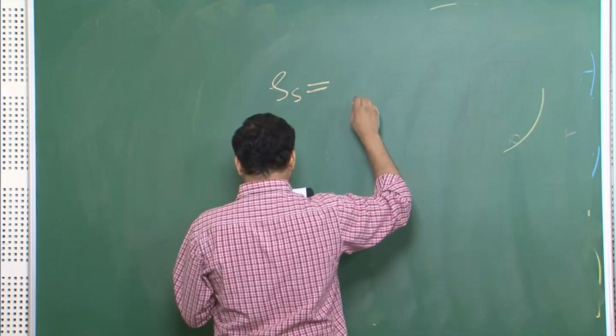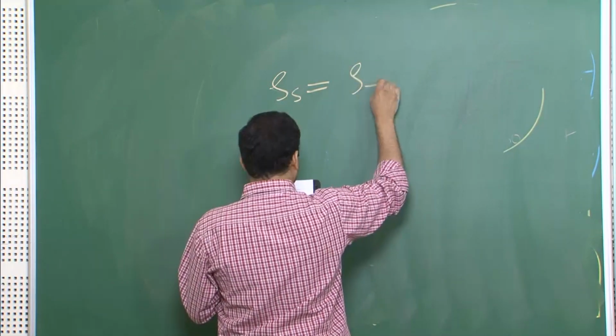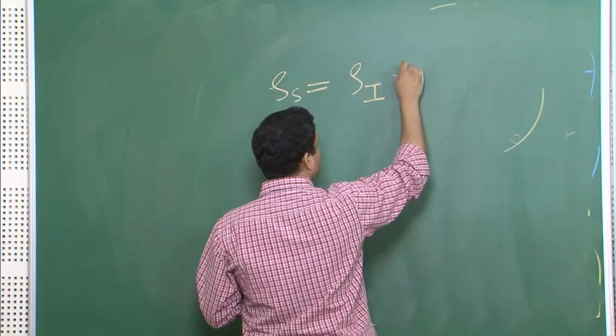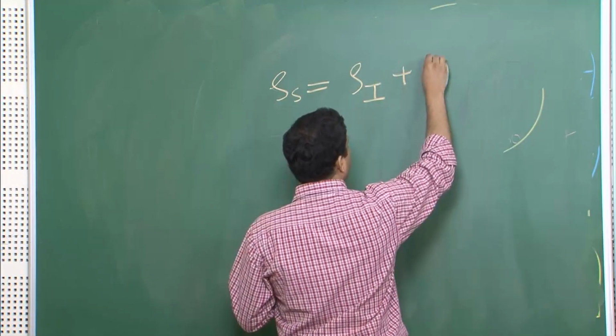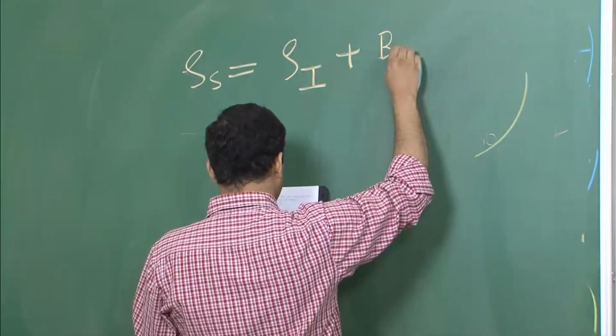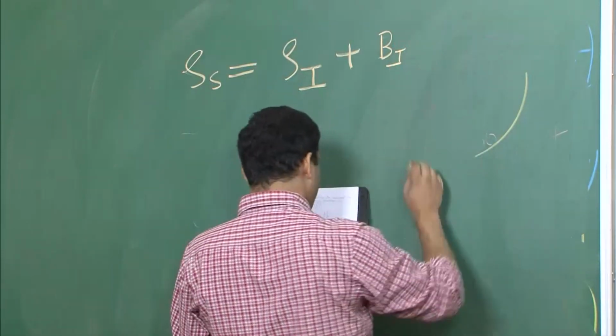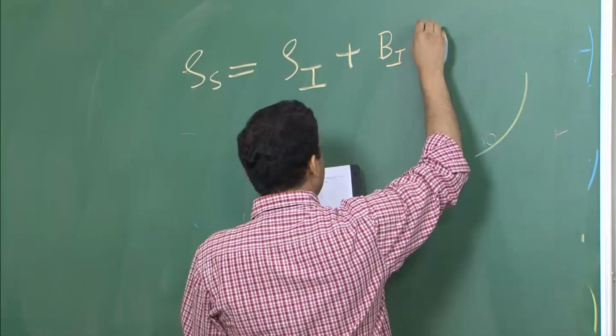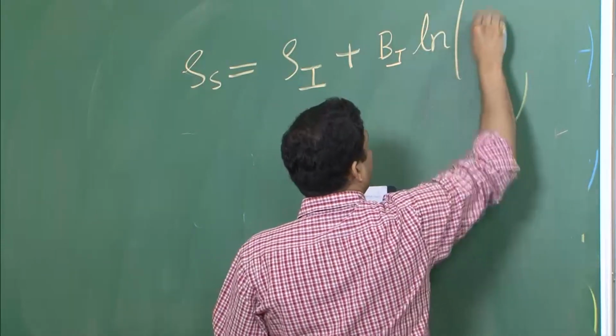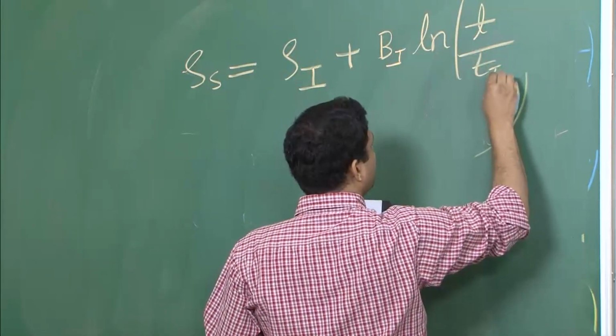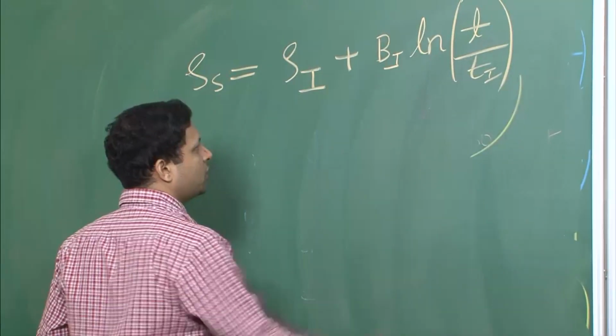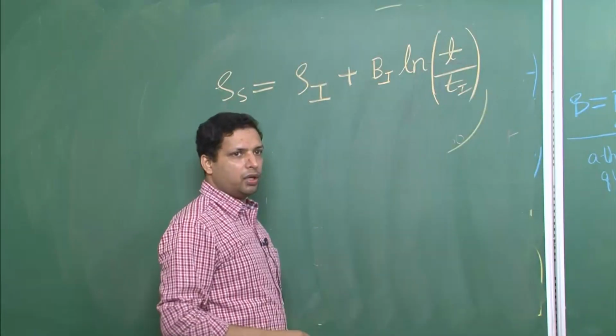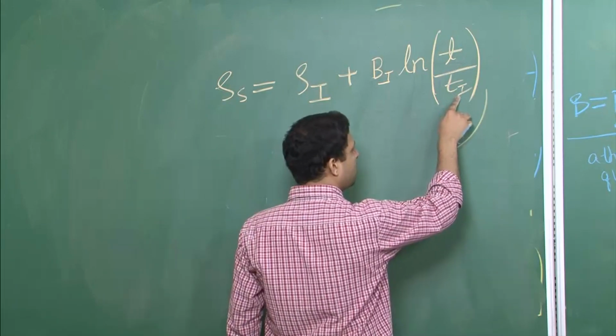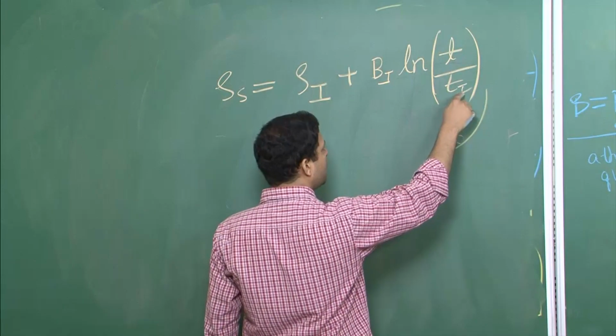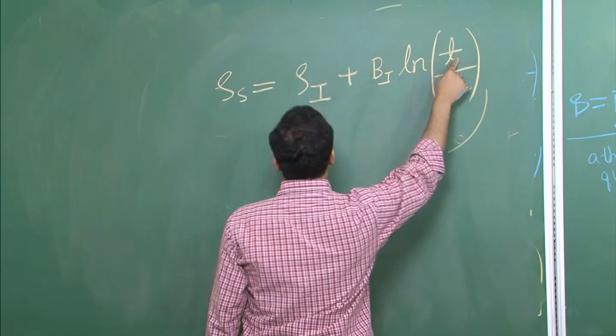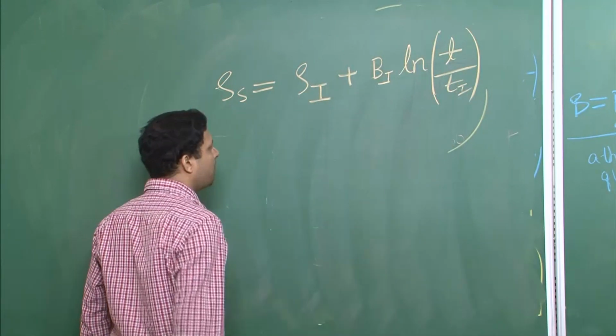So, this is the fractional density after sintering, this is the fractional density at the start of the intermediate stage, meaning at the end of the initial stage. Bi is a constant that varies inversely with grain size, and Ti is again the time at the start of the intermediate stage, meaning if you are calculating the time from the beginning, then Ti is the time at which the initial stage ends and the intermediate stage starts. So, at a particular time t, rho s would be given by this equation.